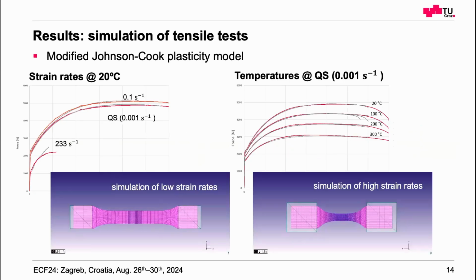Now, these are the results of our modified Johnson-Cook plasticity model. We simulated the low strain rate and the high strain rate tests. And you see for a constant temperature, here we have performed the different strain rates. Red is the real test, and gray is the simulation, and they are very well comparable, or quite the same. This is always force over displacement. Why is the force here at the high strain rate lower? Yes, because the geometry is smaller and therefore the force is smaller. We have the same diagram here with a constant quasi-static strain rate, and here you see our curves for different temperatures. And so the simulation or our plasticity model matches the real testing really well.